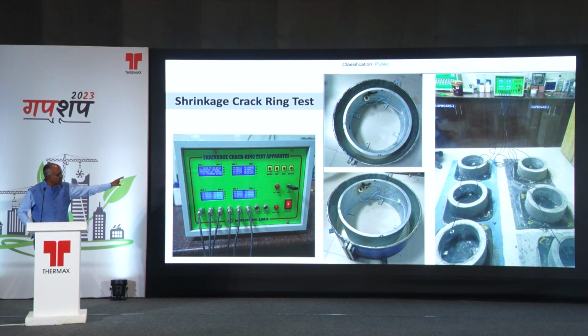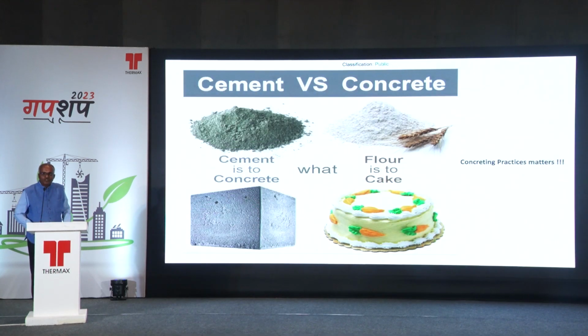What is being done is, as per the ASTM standard, the concrete mix is cast on a circular ring, and it is connected to a dial gauge, and you have a graph, and when suddenly the deflection changes, you can predict when the concrete is going to get cracked. In the sense, whether the mix has a high probability of getting cracked or not can be determined. So that can be done. So all the major deteriorating mechanisms, whether it is sulfate attack, chloride attack, or cracks, can all be measured in the laboratory. Of course, all of us know about this.